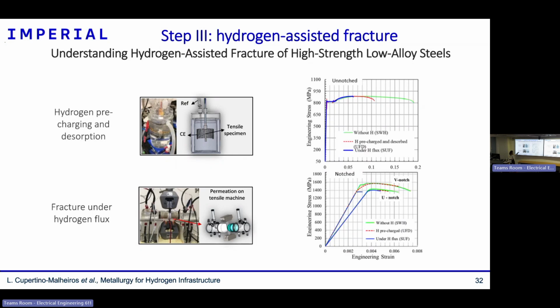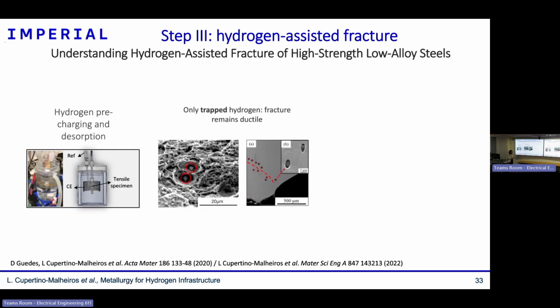All right, so the first results I'm showing you are, again, tensile curves. Here they were done for different notches, so you have unnotched specimens on the top and notched specimens on the bottom. And here what we can see is that both conditions caused embrittlement, that is, a decrease of the elongation, with the hydrogen flux, the blue curves, causing more embrittlement. Okay, the second part, I was trying then to understand that when only trapped hydrogen is present.